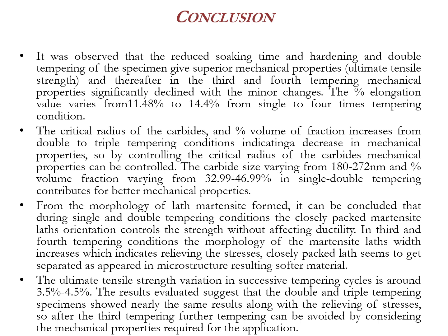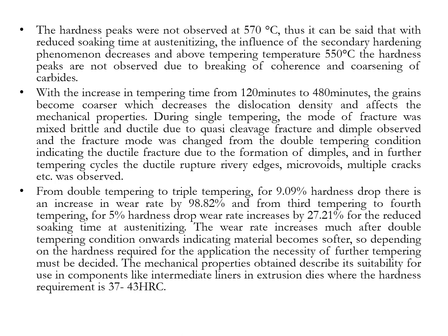Morphology observation also indicate that the closely packed martensite lath orientation controls the strength without affecting ductility in single and double tempering condition. The ultimate strength variation in successive tempering cycle is around 3.5 to 4.5%. The hardness peaks were not observed at 570 degrees Celsius. Above 550 degrees Celsius, hardness peaks are not observed.